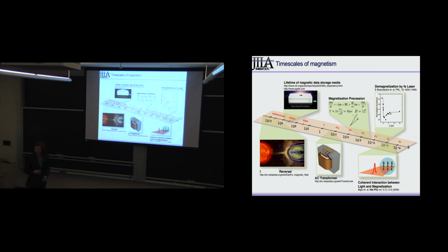Just a quick question. Sure, of course. How do you determine the electron temperature? Are you doing some spectroscopy? Yes, and I will show you exactly that. In fact, it's very simple. We just take a line out of the Fermi edge. Okay, so you look at the photoemission spectroscopy, take a line out, fit to a Fermi-Dirac, and we do this about maybe 10 femtoseconds in, so that you've got enough electron-electron scattering that a temperature is established. I see. So you're using 3 kT edge there.